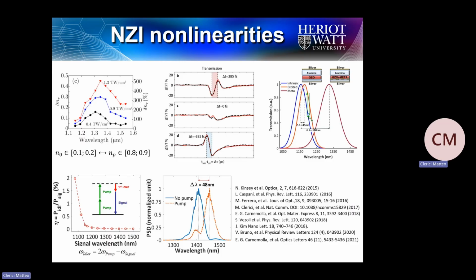And then you can time these different pumping regimes and practically kill the effect in a sort of three-state logic system. This is an example where, in a nano-Fabry-Perot, introducing 25 nanometers of gallium zinc oxide, through optical pumping we can tune the resonance of this cavity and modulate the output by 80% with an on-off time of about 300 femtoseconds. This is a 48 nanometer bandwidth shift of a transmitted ultrafast pulse, with a 40 nanometer film, performed also optically.